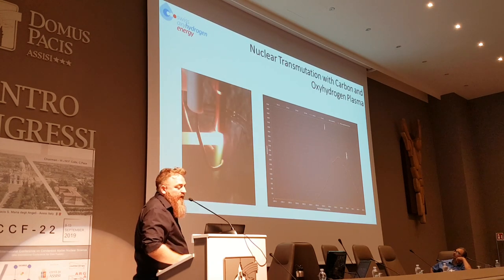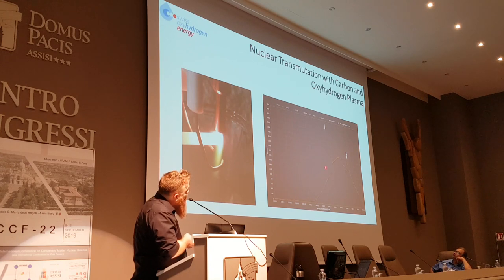Once the plasma was applied on the graphite rod, I saw a radical change in a matter of seconds. A strong sodium line appeared, also a potassium doublet here. And you can see the OH radicals just disappeared. Also you can see a really broad band around 680 nanometers.